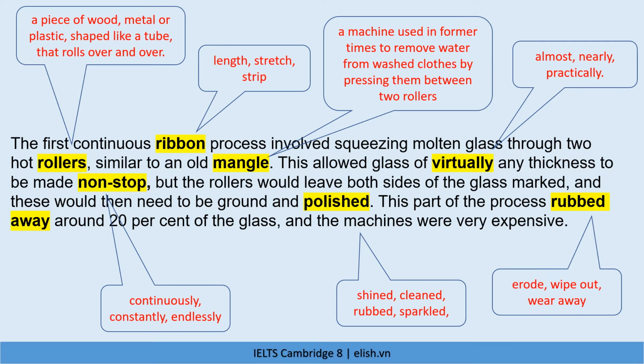The first continuous ribbon process involved squeezing molten glass through two hot rollers, similar to an old mangle. This allowed glass of virtually any thickness to be made non-stop, but the rollers would leave both sides of the glass marked, and these would then need to be ground and polished. This part of the process rubbed away around 20% of the glass, and the machines were very expensive.